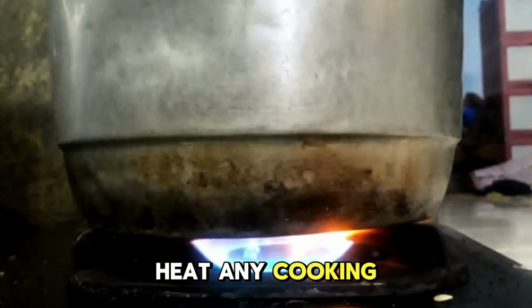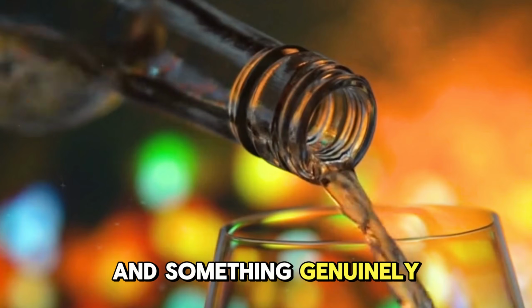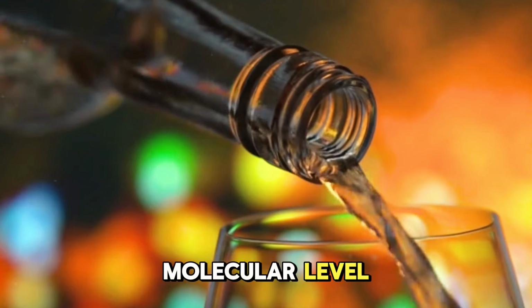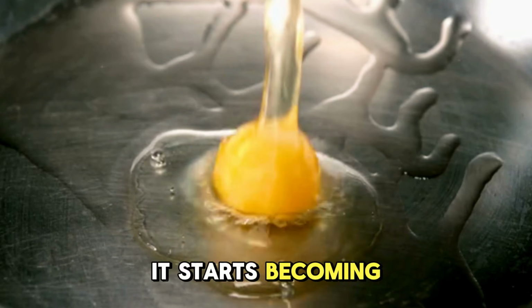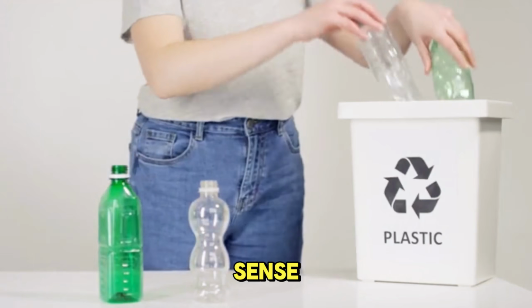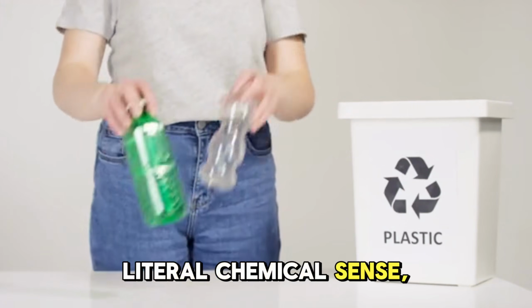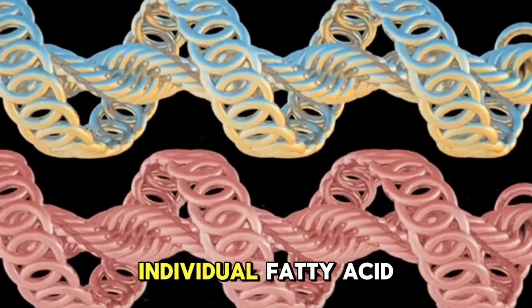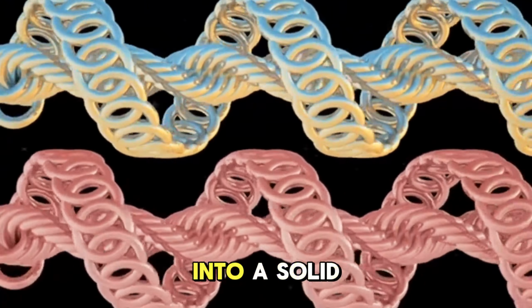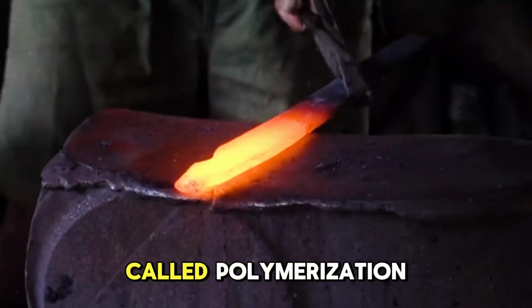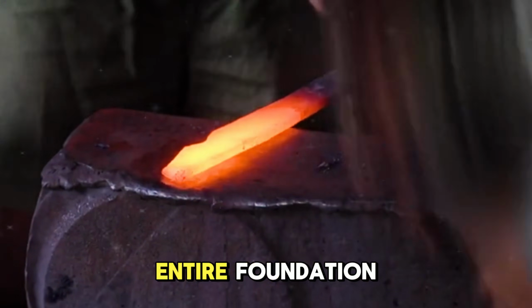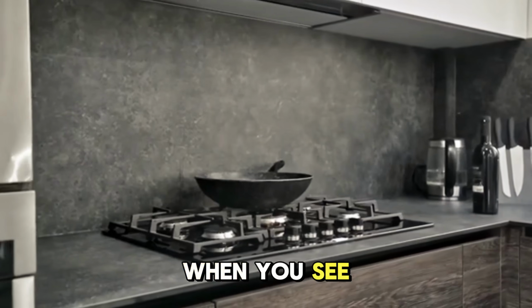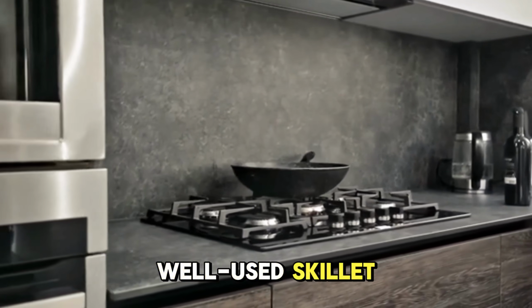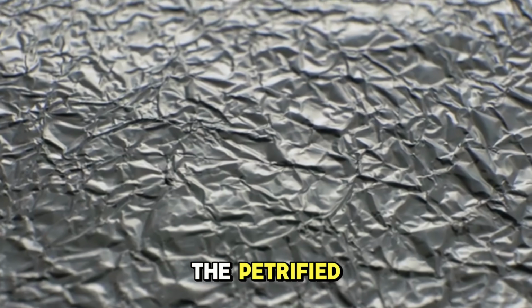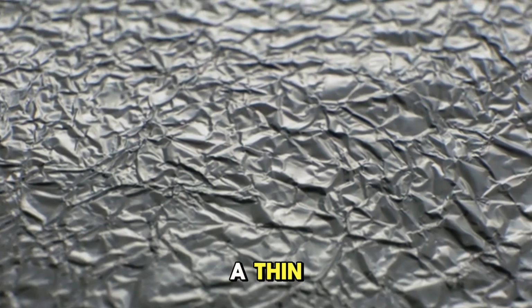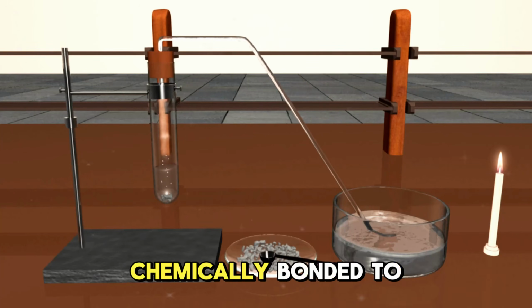Heat any cooking oil past its smoke point, and something genuinely strange happens at the molecular level. The oil stops being oil. It starts becoming plastic, not plastic in the casual sense, plastic in the literal chemical sense, a long-chain polymer network where individual fatty acid molecules have cross-linked into a solid lattice. This process is called polymerization, and it's the entire foundation of cast iron seasoning. When you see that glossy black surface on a well-used skillet, you're not looking at oil. You're looking at the petrified ghost of oil, a thin, incredibly hard layer of carbonized polymer chemically bonded to the iron underneath.